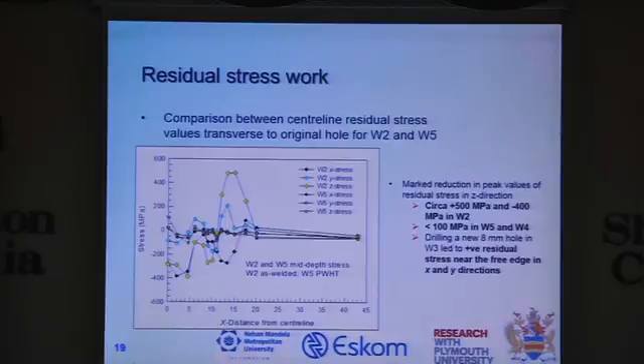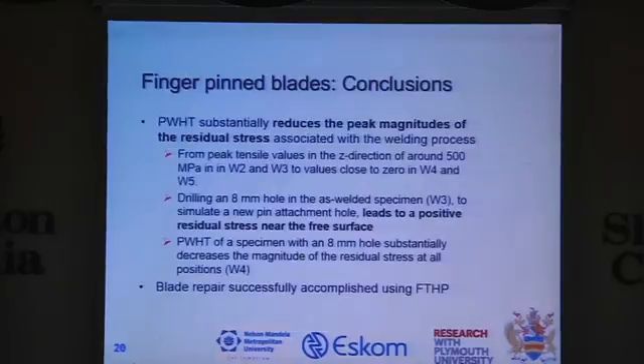I think the positive thing is that you can see that as welded, we sit with 500 MPa tensile residual stresses at about 15-60 millimeters away from the center of the hole, whereas after heat treatment you reduce that considerably to about 100 MPa. So now we're happy that we can manage our residual stresses, and we can start implementing the process onto the turbine. Alright, so in summary, what have we achieved there?